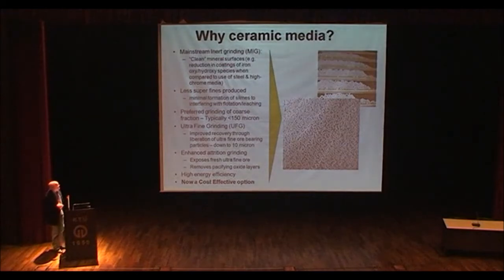The other, of course, is ultrafine grinding, which is everybody wants to get down to that last little sulfide particle. And we're talking, as I say, we can get down to 10 microns quite successfully in a very large mill. IsaMills produce a 10 cubic meter unit. It's 1.8 meters in diameter. It can have up to 18 tons of 5 millimeter balls in it, or 3 millimeter balls. And it's a single pass, and the material is in there for approximately 30 seconds.